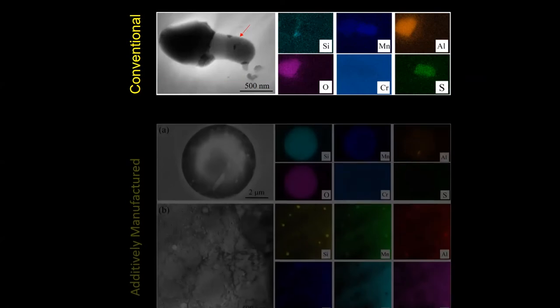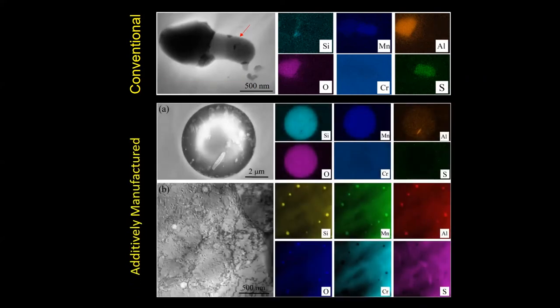Pitting corrosion usually starts at a very tiny region of the material and then grows up. These tiny regions are usually inclusions, and most importantly, manganese sulfide inclusions. This inclusion is a very small one with a few micrometres in dimension, and the tail of the inclusion means leaching manganese and sulfate. However, interestingly, for the additively manufactured material, you couldn't find any trace of these detrimental manganese sulfide inclusions.